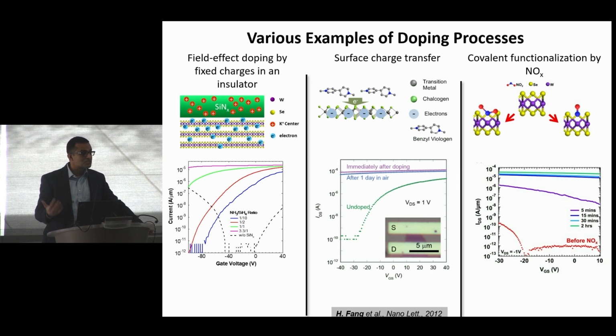And there were theoretical studies being done to understand why the mobility of tungsten selenide is low and moly sulfide is high. It had nothing to do with mobility. It had to do all with contacts. The mobilities were not extracted correctly. The contacts were shoddy for tungsten selenide. So once we were able to dope the semiconductors heavily, we were able to form better contacts, and we were able to get high mobilities with tungsten selenide.